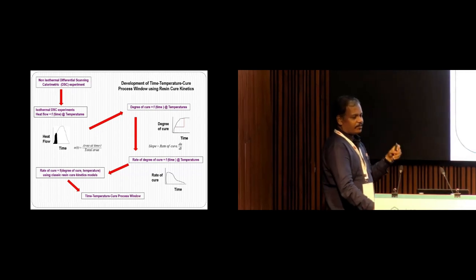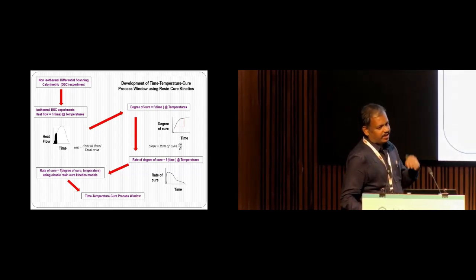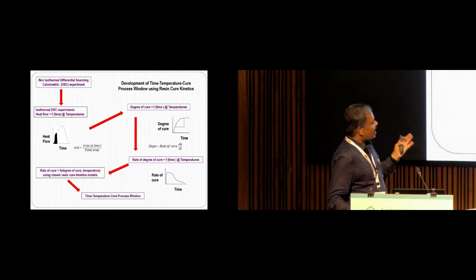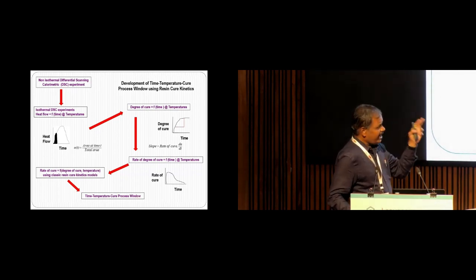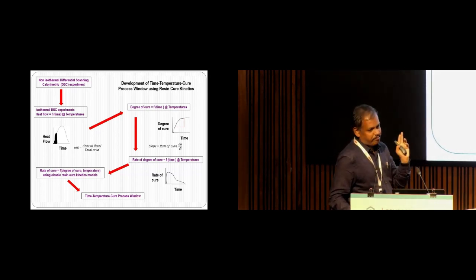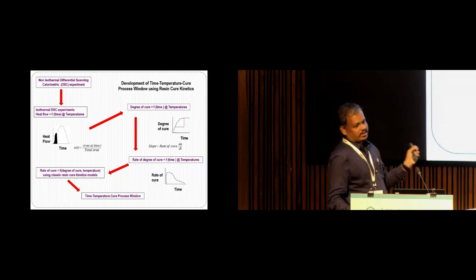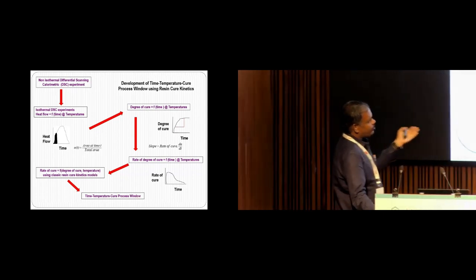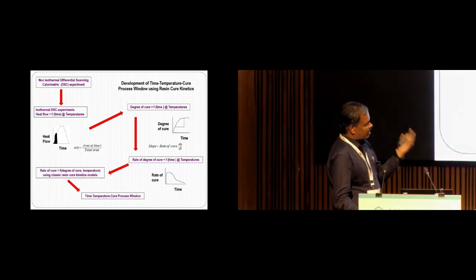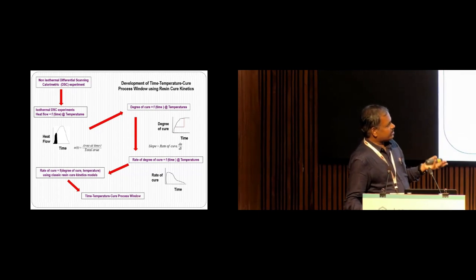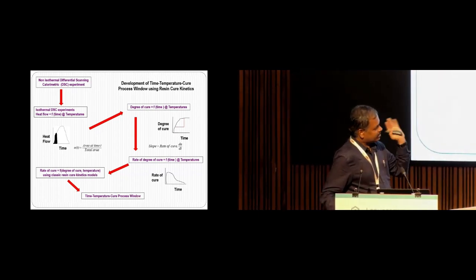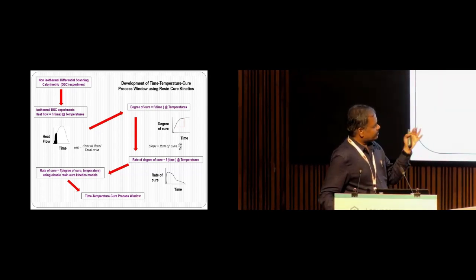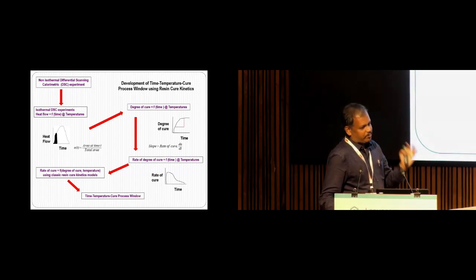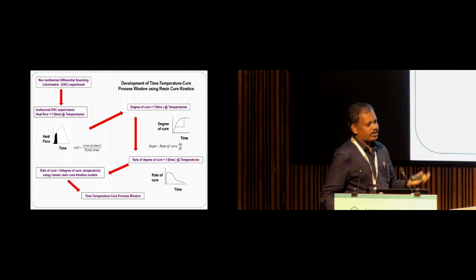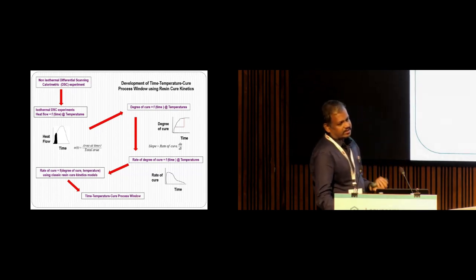Once I get the degree of cure as a function of time at different isothermal temperatures, I have to take the slope at every instant of time, and if I plot it, that will give you d alpha by dt, which is nothing but the rate of cure. Using classical curing kinetics equations, the rate of cure is modeled as a function of temperature and degree of cure. That will give you the classical curing kinetics modeling.